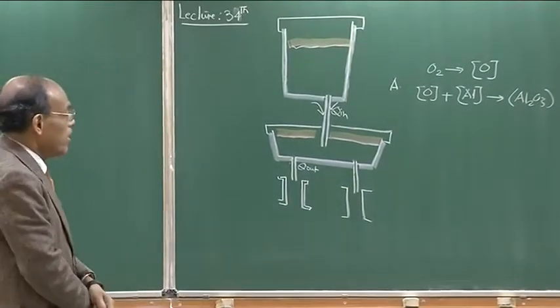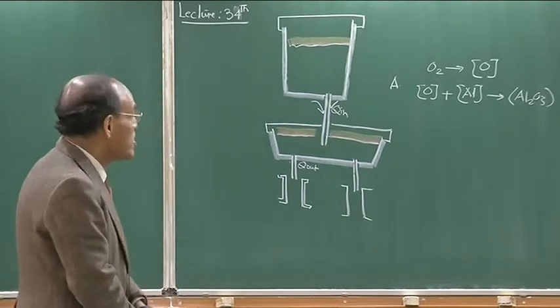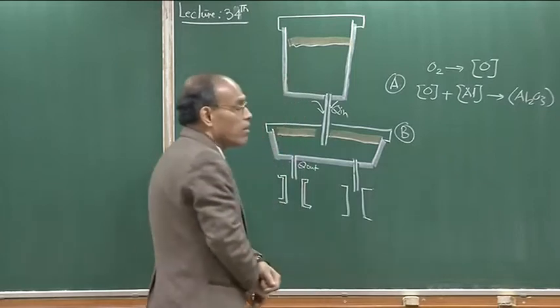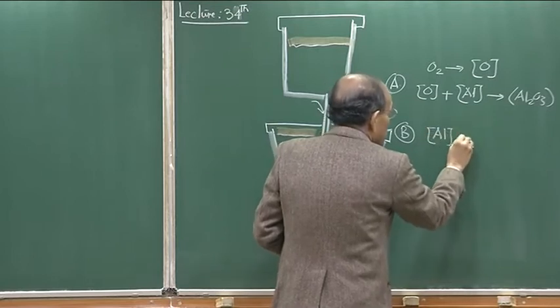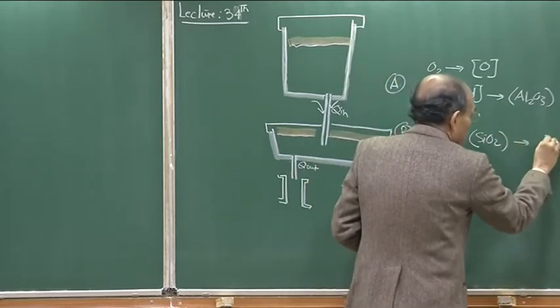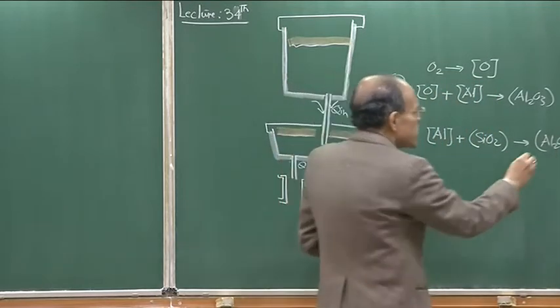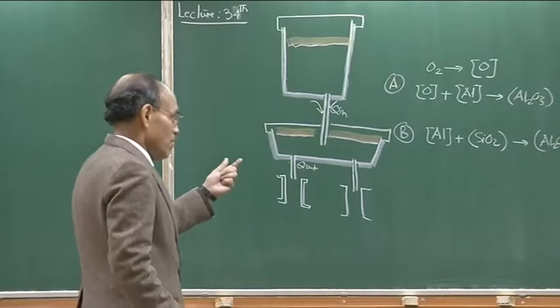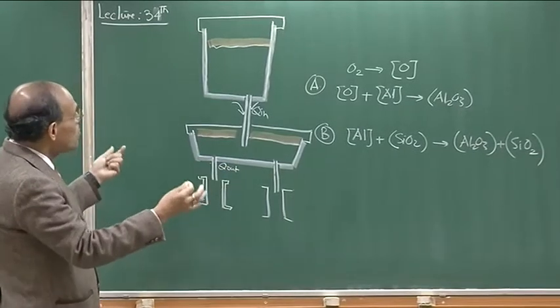The same reaction applies to dissolved magnesium or dissolved calcium. Aluminum, calcium, and magnesium are the three most reactive elements present in steel at this stage. A parallel route of reoxidation is the chemical reaction between dissolved aluminum and silica present in tundish powder, producing Al₂O₃ and SiO₂. From this standpoint, a tundish really cannot be regarded as an inert reactor.